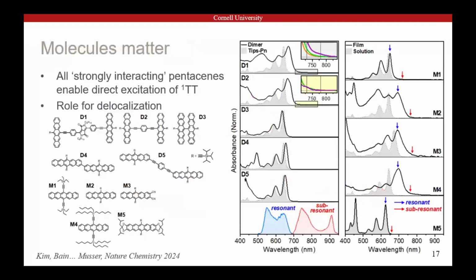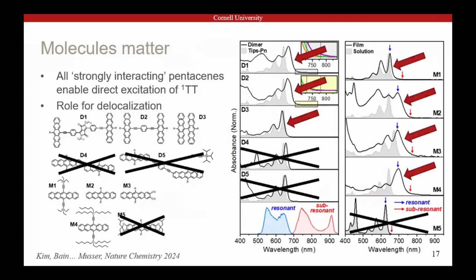So that's great. We can go back with the understanding we really are pumping this triplet pair state now and think about what the different molecules are telling us. Because one of the most exciting things for us was that it didn't happen all the time, because that means there is some materials design principle behind it. And very crudely, we can look through and see, well, the ones that enable this direct excitation of the triplet pair, they're the ones that have the larger shift between uncoupled isolated molecule and thin film or dimer. So there's the largest intermolecular coupling between the pentacenes. So that tells us there's maybe some role for delocalization of this initially excited state.